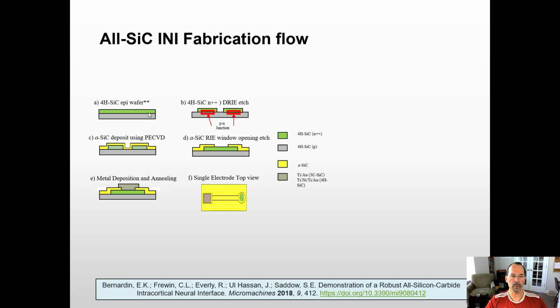So how do we make the device? Well, we start out, again, we make our PN junction, we form mesas with deep reactive ion etching, and then we coat with amorphous silicon carbide, followed by opening windows in the amorphous coating with RIE, and that's for the business end, that's for the part that contacts the brain. And for the packaging end, we do use Ti/gold to form a good connection to the package, which would be outside of the brain.